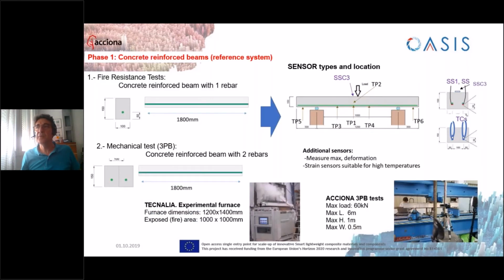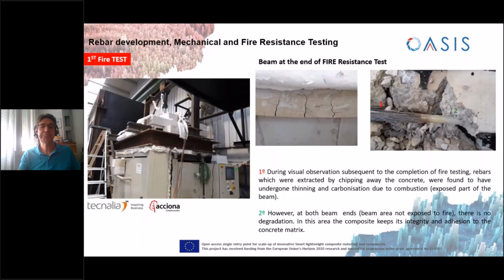So once the fiber-reinforced polymer rebars have been fully characterized at the rebar material scale, the next step is to integrate them in concrete beams and evaluate their mechanical and fire-resistant performance. In this showcase, there is a very close collaboration between the end user and the pilot lines. For instance, Acciona defined the geometric dimensions of the sample for each type of test, either mechanical or fire-resistant, and installed the different types of sensors to measure deformation and temperature in different parts of the rebar during testing. After that, the test procedures and results are shared among all partners involved in this showcase. This helps to improve and get the most valuable and meaningful information for the next round of tests.